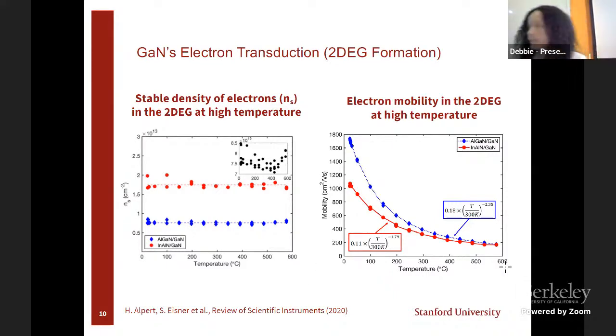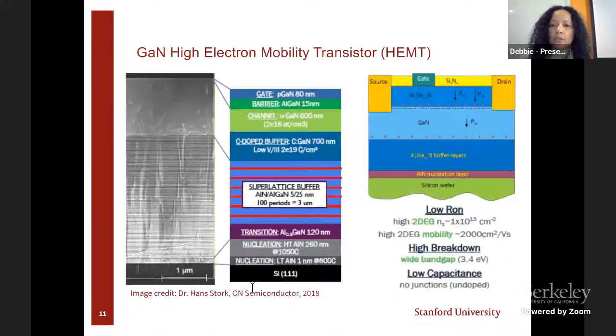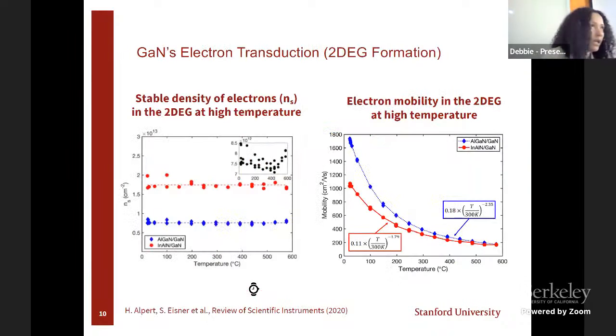And then, of course, our mobility does degrade, as with any semiconductor material or transport of electrons, due to scattering effects. That's just the nature; we can't really get around that. So we do have mobility degradation, and depending on the type of device, that might be important. But nonetheless, we do have carriers from room temperature up to 600 degrees Celsius. These are the two knobs that we look at and try to understand when we start to stimulate these types of devices with the external environment. Yeah, that's an ongoing question. I'll talk about the failure modes, but our longest test has been around 10 days or so. That's pretty good, but still lots to do, and I'll touch on that throughout the talk.